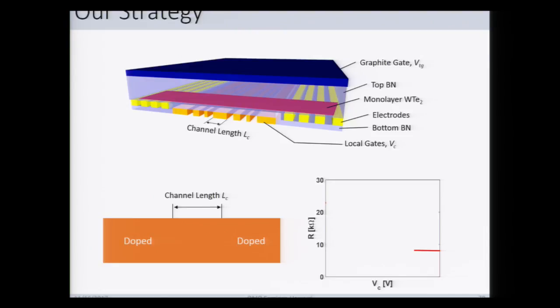So that goes as follows. We first energize the top graphite gate to have doped 2D electrons everywhere in the tungsten telluride, and we measure some resistance. And then we take this local gate that has a fixed dimension and start to deplete that area of the sample back into the band gap of the material. And as we do so, the resistance starts to rise. If this is a simple insulator, then the resistance should go up ad infinitum. If it's a Dirac system like graphene, it should come right back down.